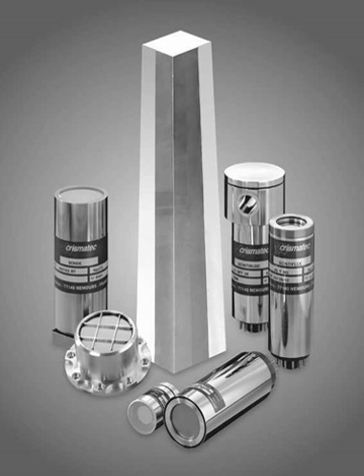Both of these components can also be a function of the energy loss dE/dx. In cases where this energy loss dependence is strong, the overall decay time constant varies with the type of incident particle. Such scintillators enable pulse shape discrimination, i.e., particle identification based on the decay characteristics of the PMT electric pulse. For instance, when barium fluoride is used, gamma rays typically excite the fast component, while alpha particles excite the slow component. It is thus possible to identify them based on the decay time of the PMT signal.